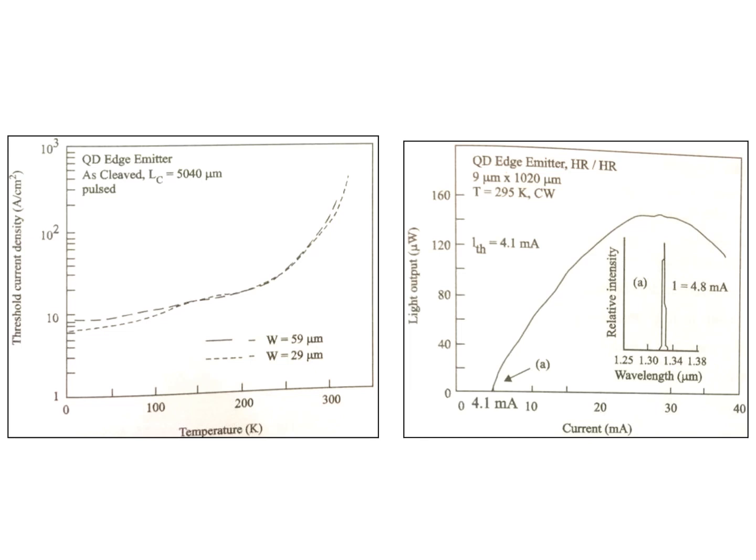In a practical quantum dot laser structure, the injected carriers can thermally escape from the lowest state, that is the ground state, into the excited state, the wetting layer, or even jump out of the heterostructure. As a result, the recombination processes of the carriers give rise to an additional component of threshold current, which depends exponentially on temperature.